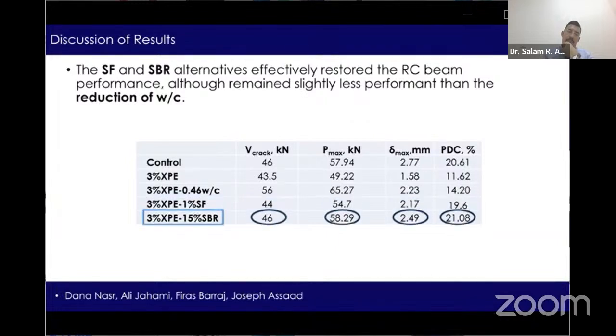Whereas when 15% SBR was used, the values reached 46 kilonewton for V crack, which was equal to the value of V crack for the control mix, 58.29 kilonewton for Pmax that exceeded the value of Pmax for the control mix, delta max reached 2.49 millimeters, and PDC reached 21.08% and exceeded the value of PDC corresponding to the control mix.